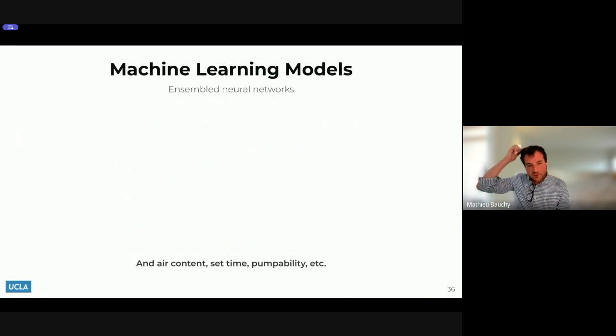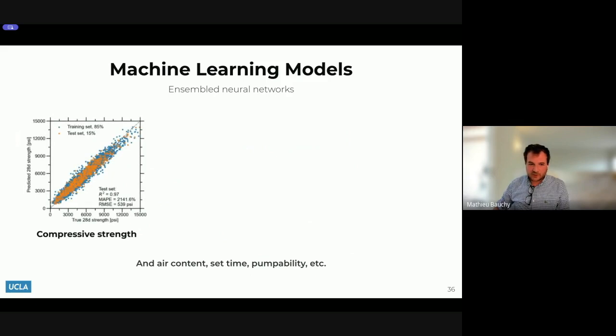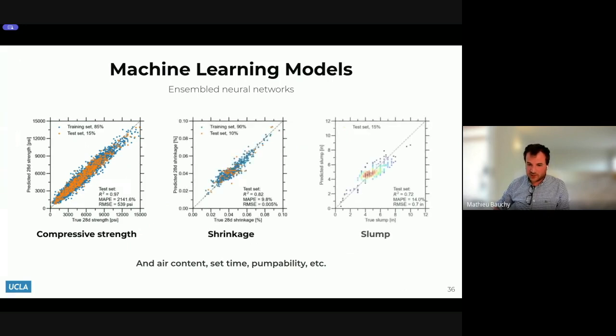So let me show you a little bit of actual results. Here I'm showing the prediction versus true properties. And again, we need to do that for several properties: strength, shrinkage, slump. When we look at this, it gives us an idea of how good the model is. We don't expect an R square of 0.99 or anything like that, because in this case we are satisfied when the accuracy of the model becomes comparable to the uncertainty of the measurement itself.